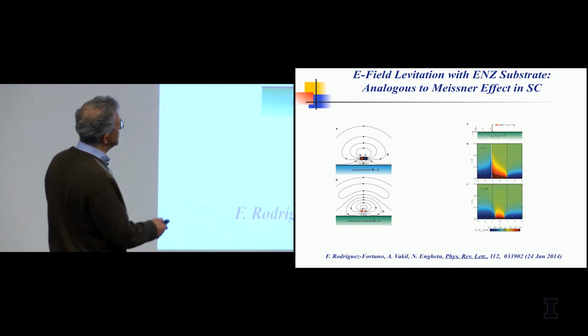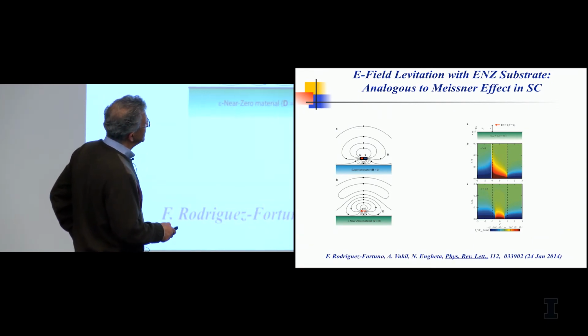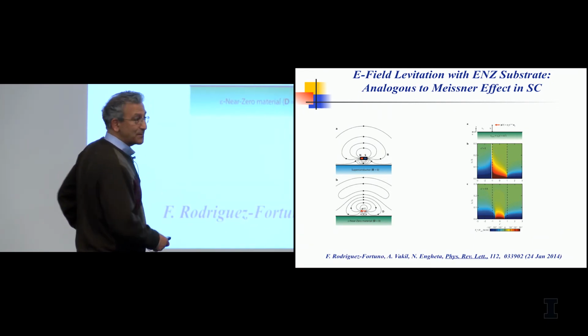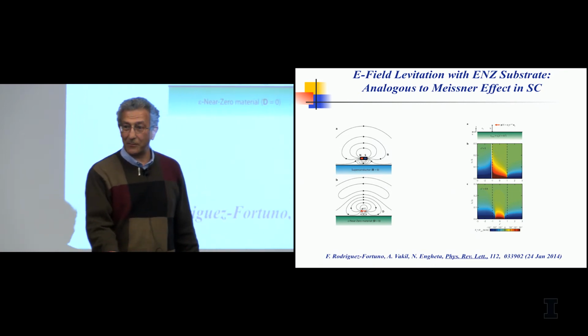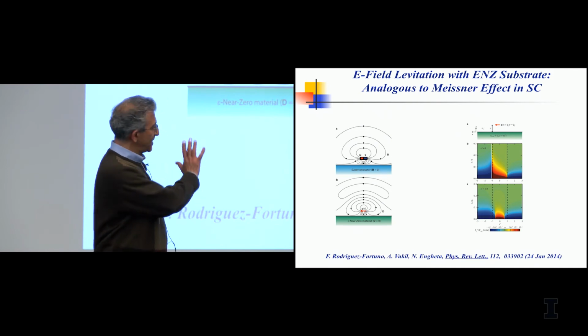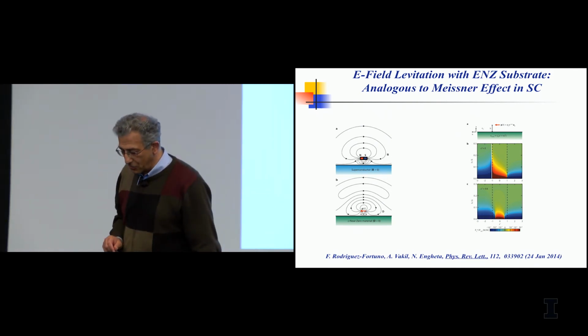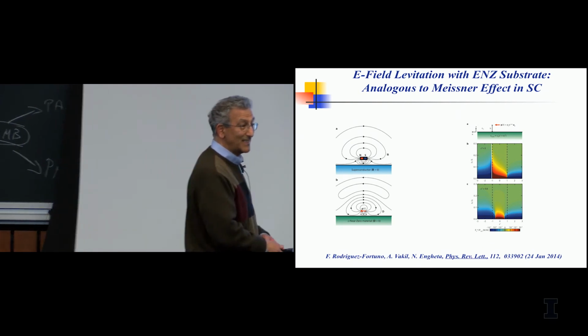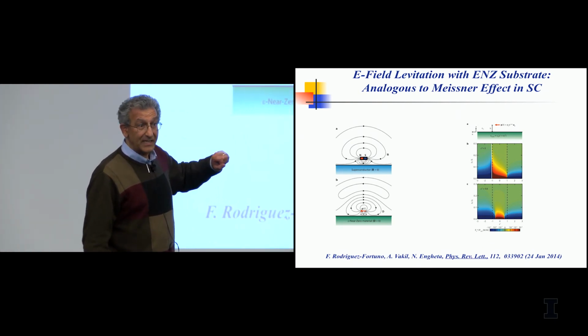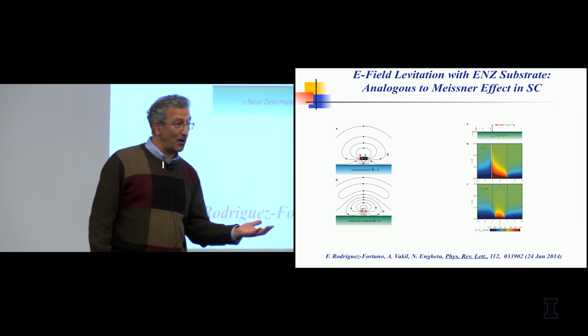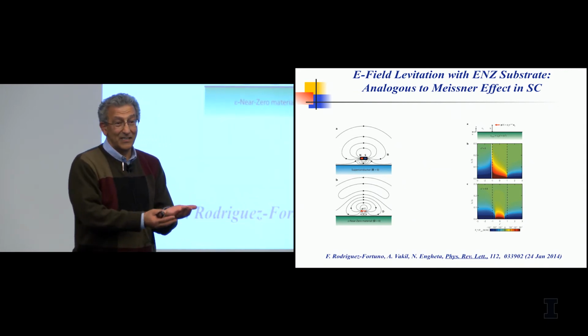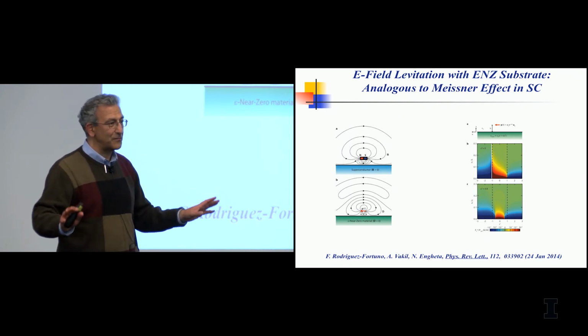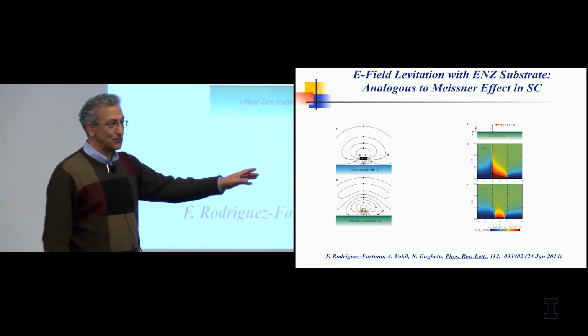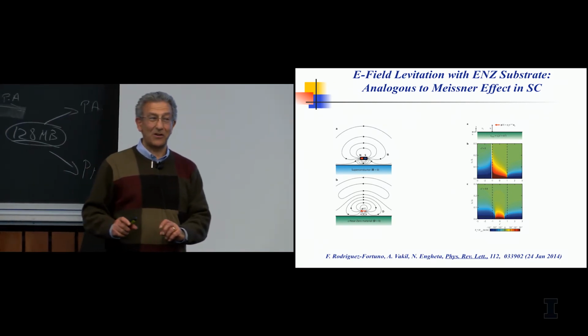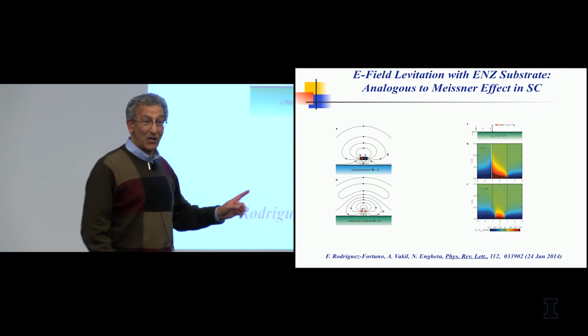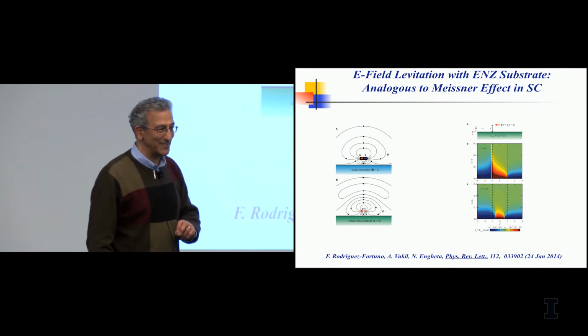So if you put an electric dipole on top of this, the electric dipole should be levitated. We theoretically proved this, by the way, in this paper, and we showed that indeed there's a very interesting range of permittivity of the substrate such that an electric dipole on top of it could be levitated. Now, this is theory so far, but we are working with my friend Pino Strangi at Case Western Reserve University to try to show this experimentally. If we can levitate the particle by just shining laser light over here, you can completely remove the friction. And you can have a microfluidic system to walk over there, kind of like the nano system of magnetic levitation. But this would not be magnetic levitation, it's actually electric levitation.